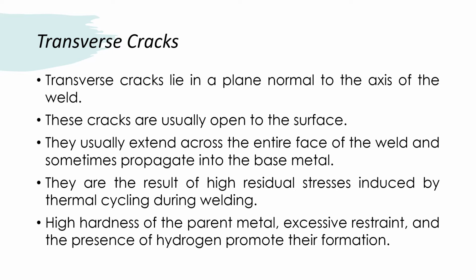High hardness of the parent metal, excessive restraint, and the presence of hydrogen promote their formation.